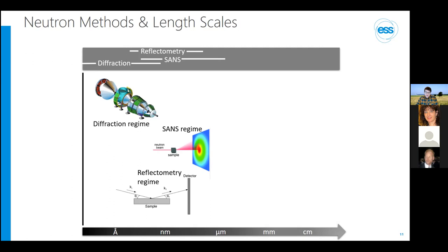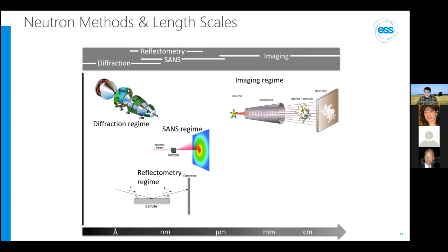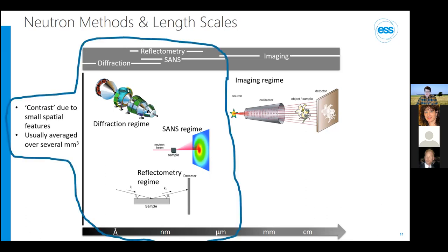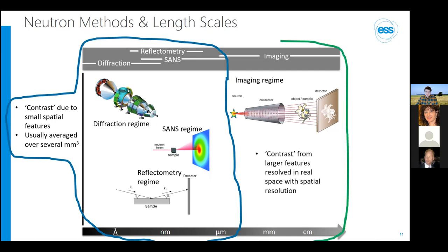All of these scattering measurements are performed in reciprocal space or Fourier space, while neutron imaging, on the other hand, is actually performed in real space, and the accessible length scales are determined by the achievable spatial resolution of the instrument, which nowadays is as good as a few micrometers. And of course, neutrons can shine through tens of centimeters of material. Moreover, scattering techniques usually probe average volumes of the material, while imaging is a spatially resolved technique, as I just explained.